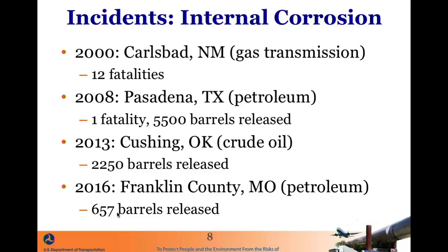So I want to highlight some of the significant internal corrosion incidents. The real game changer in the industry was the 2000 Carlsbad, New Mexico incident where 12 people died camping next to a gas transmission pipeline in a Class 1 location in essentially the middle of nowhere. But they were right next to a segment of the line which collected a lot of liquids, and that caused internal corrosion of this line, which was not subject to inline inspection. We passed new regulations since then, which I will focus on to help prevent an incident like that from occurring again. And this is a partial list of some of the other incidents here involving liquid lines. As you see, most of the significant incidents are smaller releases.